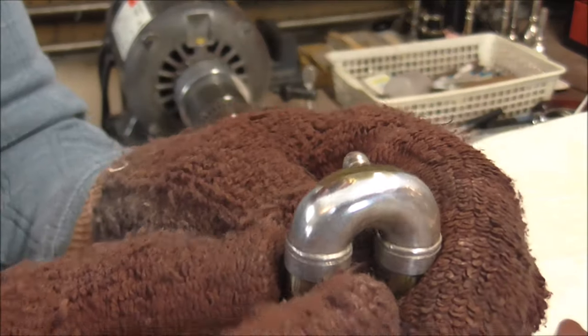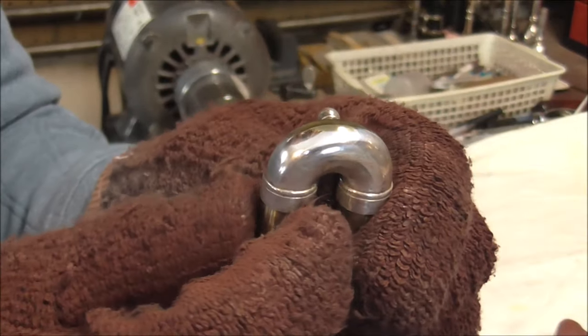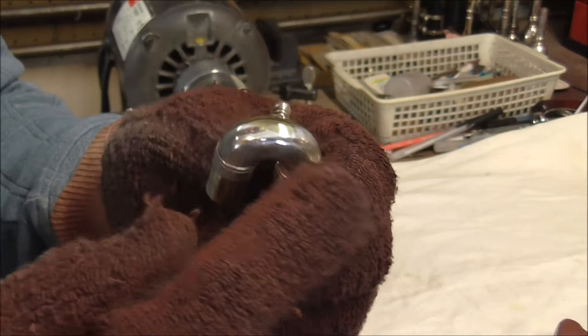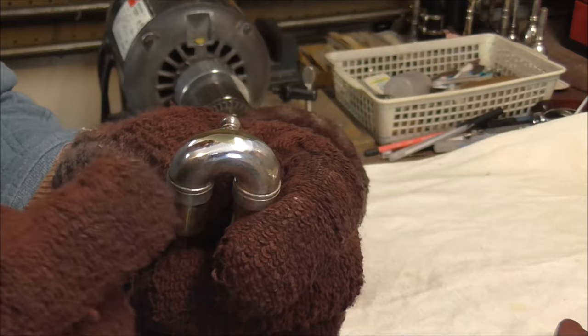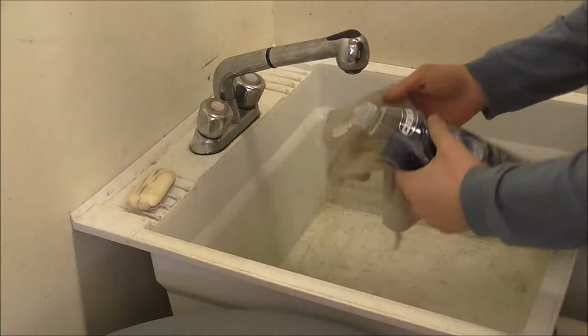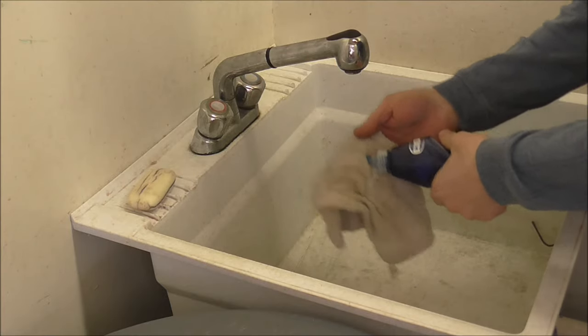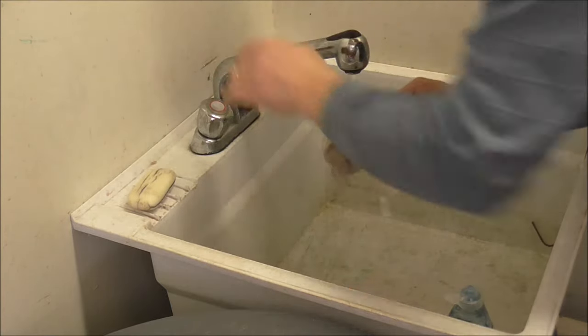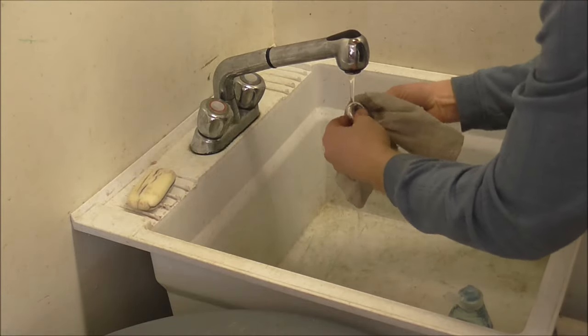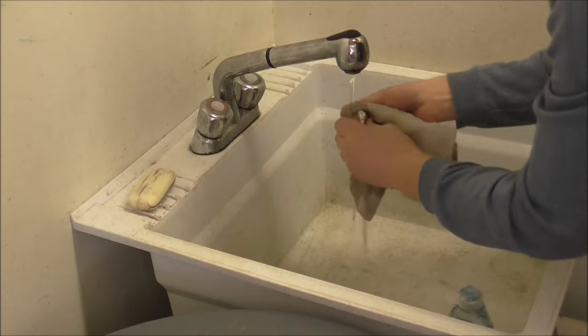It is shiny and it is almost ready to be plated. The red rouge buffing compound leaves a very fine layer of residue on top of the surface, and in order for the plating to stick like it is supposed to, I need to clean that up. The instructions said to wash it off with some dish detergent, so I am going to do that. That cleans off the layer left from the red rouge buffing compound.